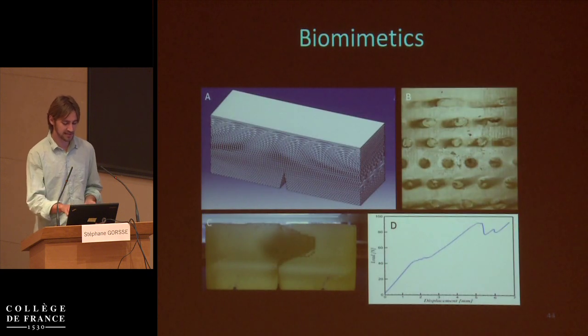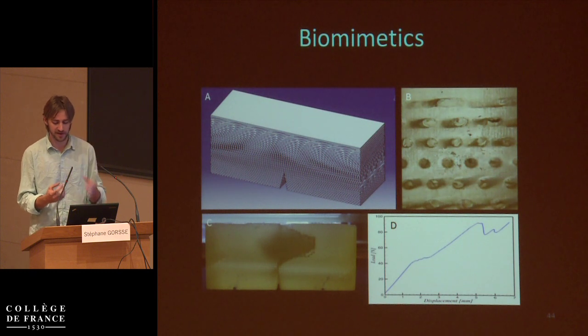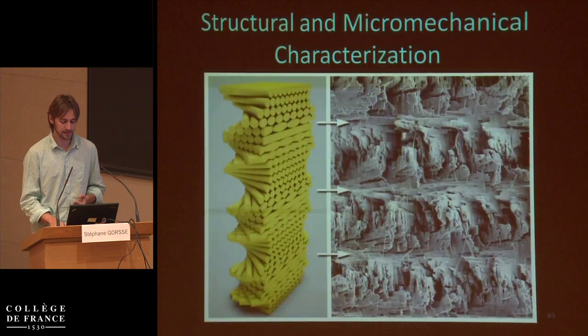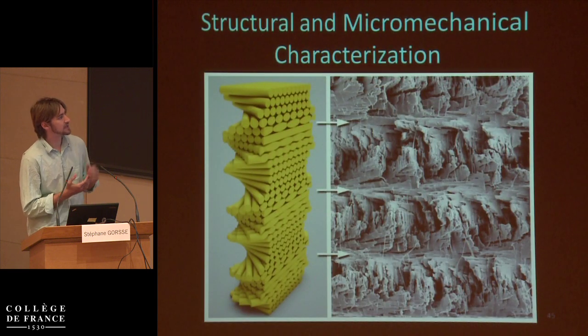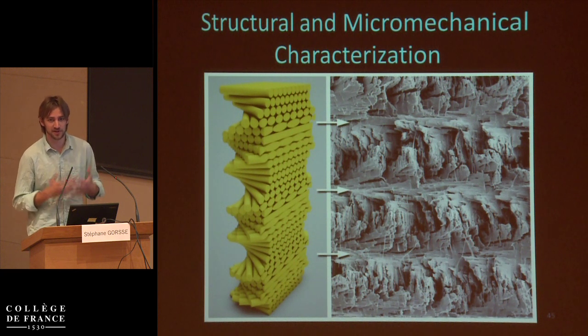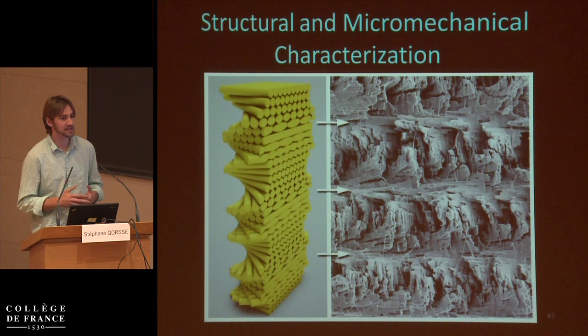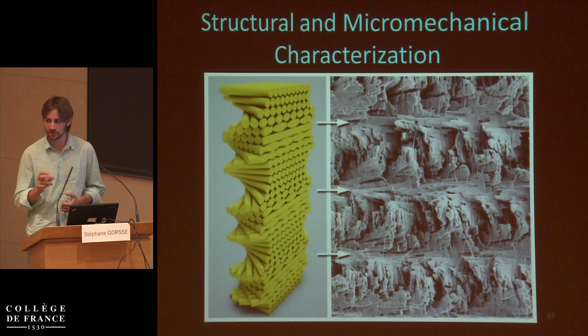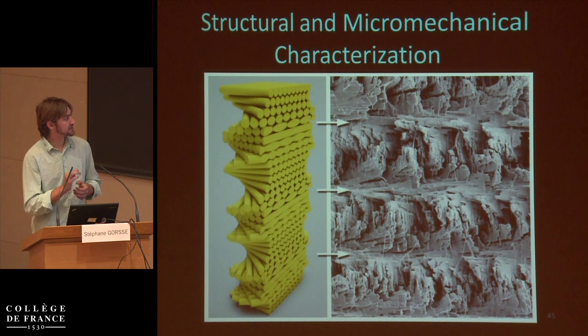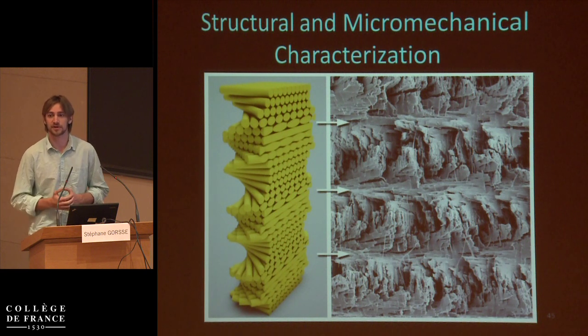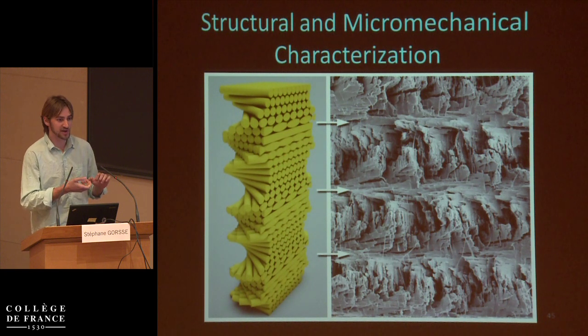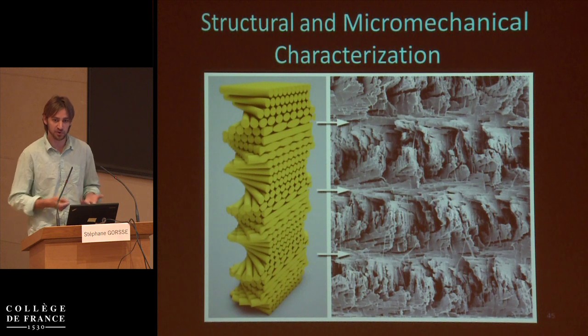And one place that we got lucky here is that this wouldn't have worked if the bonding between the fibers and the matrix wasn't sufficiently strong. And that's kind of intriguing as well, because if you think of fiber reinforced composites and the current status quo and the thinking of why we make fiber reinforced composites, it's to enhance the toughness of your epoxy, or whatever you're using as your matrix. But one of the most predominant mechanisms is fiber pullout. And there's been a lot of work to tune the oxidation of glass fibers such that the friction between the matrix and the fiber is just under the strength of the fiber. And what that means is that you want to have it as strong as possible such that you dissipate as much friction energy as possible while you're pulling your fiber out, but then you don't want it to exceed the strength of the fiber, because otherwise you sever it.